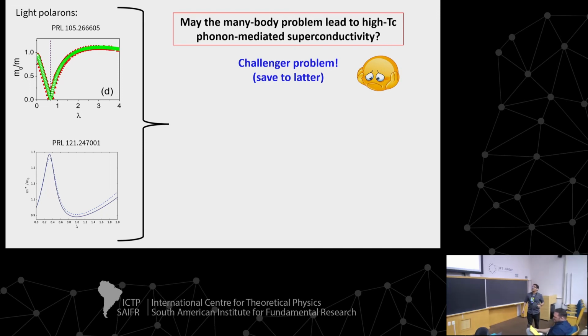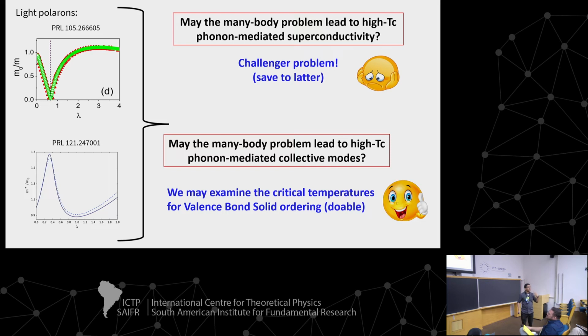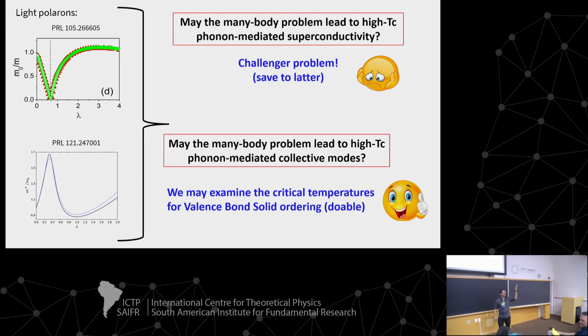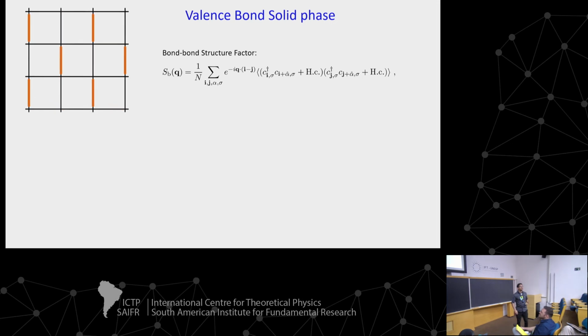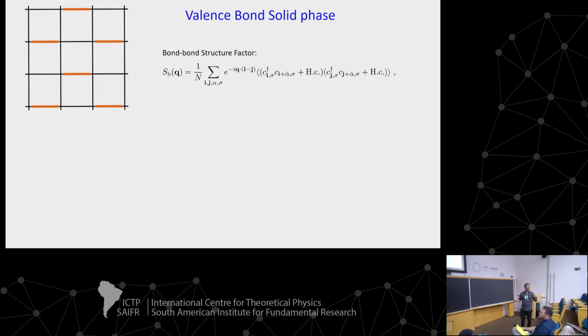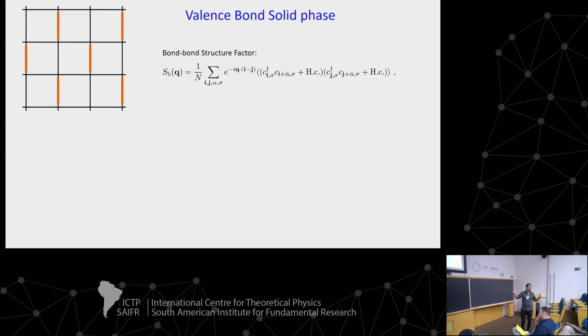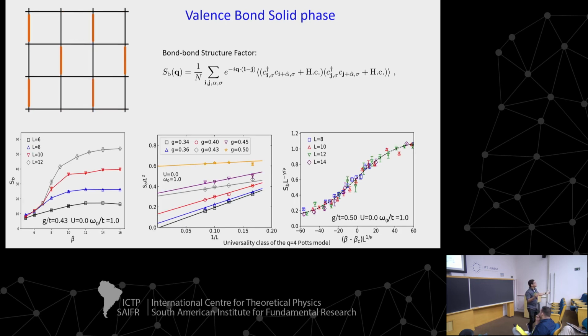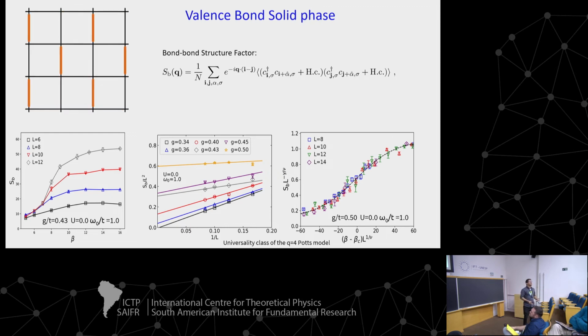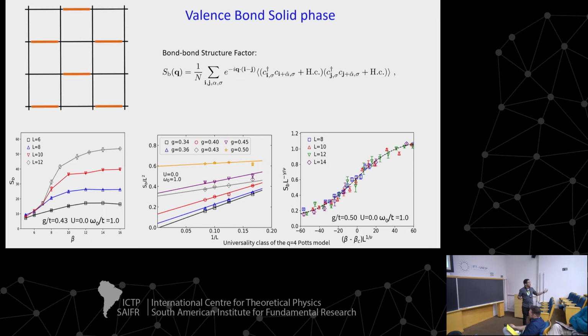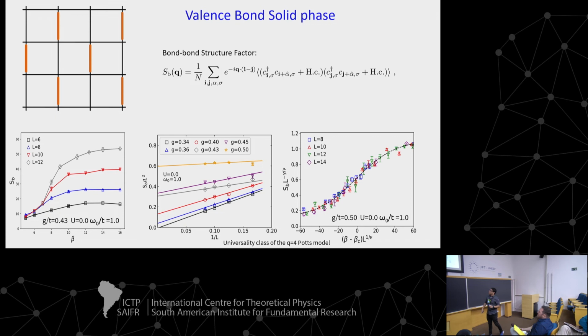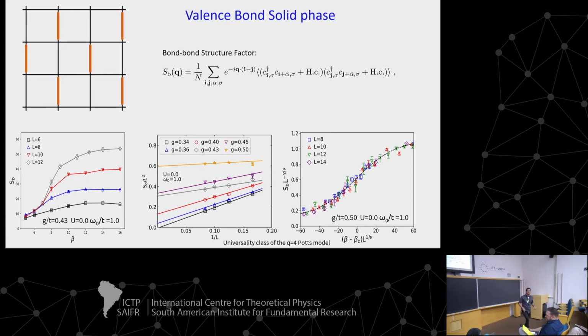But I can change the question. Can I try to analyze long-range order for other kinds of collective modes, such as valence bond solid or charge density wave? Because the mechanism is the same. If I can have high temperature transitions to valence bond solid or charge density wave, probably I can have the same for superconductivity because the mechanism is the same. And this is what Sebastião is doing in his PhD. We are analyzing the formation of valence bond solid, and we can analyze it by the bond-bond structure factor. And I will skip all of these details about Monte Carlo stuff, but basically we can investigate the transition, analyzing this by the Potts Q equal 4 model, and we can collapse the data and see the critical exponents, blah, blah, blah.